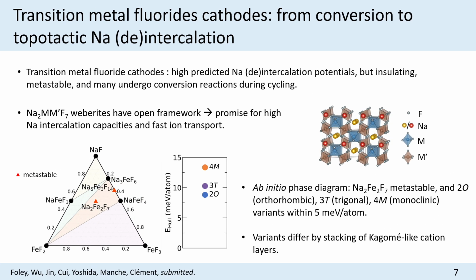So we were particularly interested in earth-abundant, sustainable cathode chemistry, so we started to look at this sodium iron fluoride system, Na2Fe2F7, and you might remember from Christine's talk that polymorphism is a thing in material science, and metastability as well. For this particular material, if you look at the phase diagram that we've computed with first principles, this Weberite structure is actually metastable by at least 10 meV per atom above the hull, so it's slightly metastable. The problem is that there are 3 polymorphs to account for, and these 3 polymorphs are within 5 meV per atom from each other. What that suggests is that if we try to make this material, we might be making a mixture of these polymorphs instead of a single polymorph. These polymorphs only differ by the stacking of the cation layers.